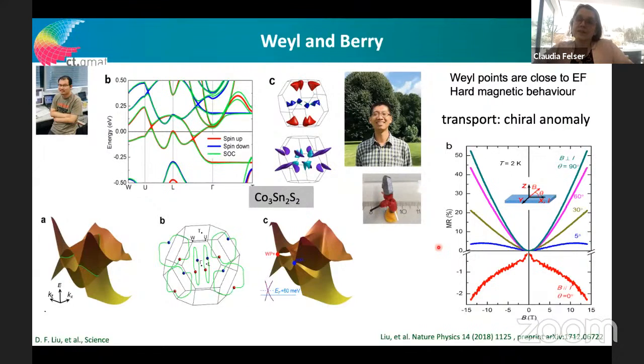So the smoking gun experiment, which we didn't plan on this material, but which was forced by the editor, was that we should show the chiral anomaly in this compound, which means we should have a positive magnetoresistance effect when the magnetic field is perpendicular to the current, so a normal Hall measurement, and it should be a negative magnetoresistance effect when the B field and the current are in parallel.